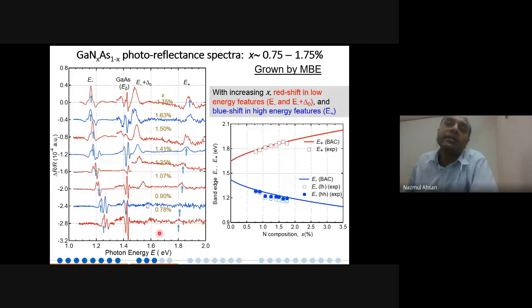that tells that in gallium arsenide, if you dope, this is experimental, we have grown single crystalline high quality gallium arsenide nitride material on a gallium arsenide substrate. We call this heteroepitaxy. You have high quality material, and we really want to check if we do have 2 band gaps.